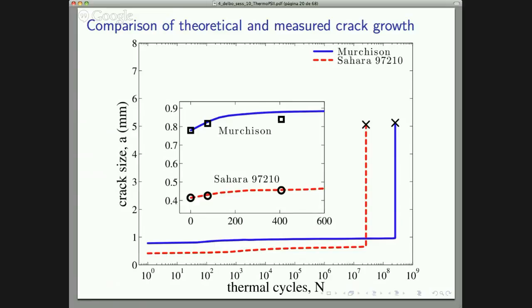We developed a theoretical model that matched. We put the thermomechanical parameters in this model. The model is not fit to the experiment, but we could reproduce some of the crack growth in our experiment, not perfectly. We took literature data for the thermal and thermomechanical parameters, developed the model, and compared it to the experiment.